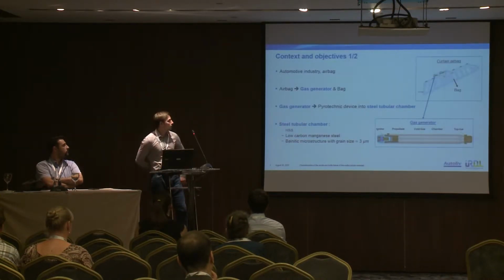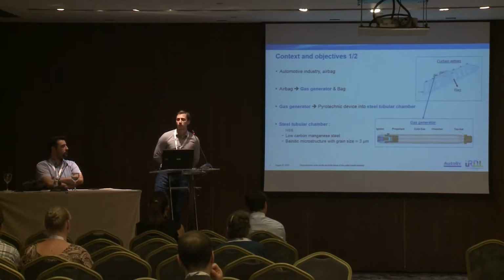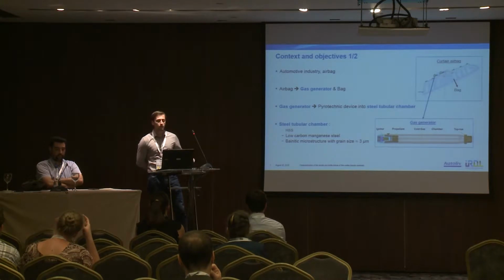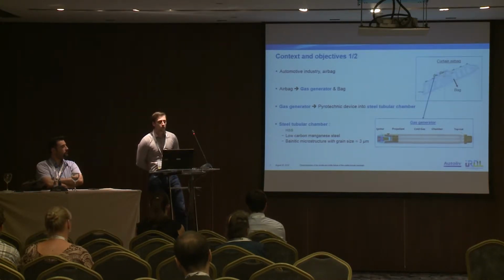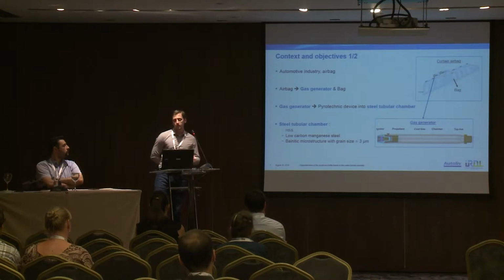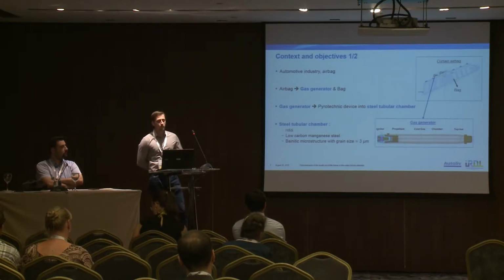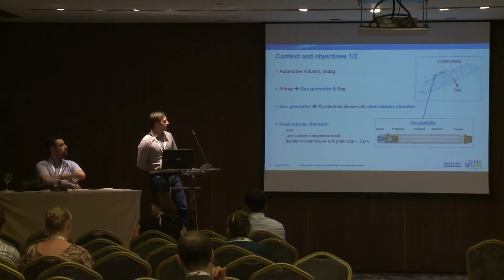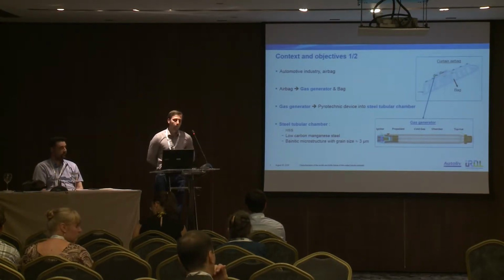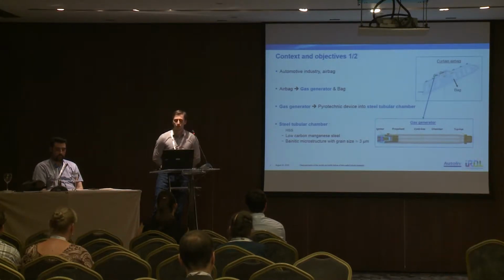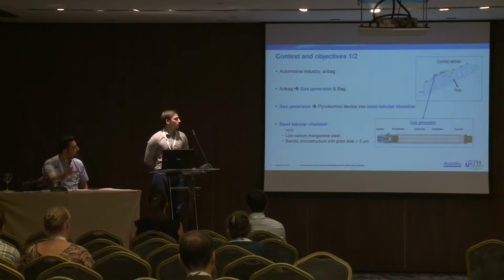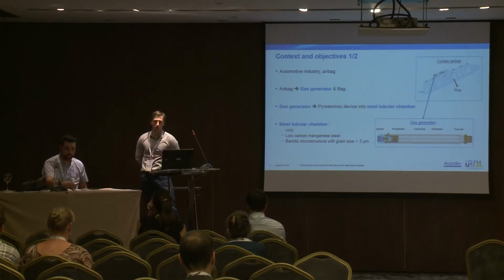So let's start with a short introduction of this topic. I'm working on airbags, which are made from a gas generator and a bag. The bag is inflated by the gas generated with pyrotechnic devices. The gas generator is made from, of course, pyrotechnic devices, but also a steel tubular chamber. And this chamber is the key problem for the company. Why? Because we have a steel tubular chamber made from a high-strength, low-carbon manganese steel, with a bainitic microstructure. There is a very thin grain size, close to 3 micrometers.